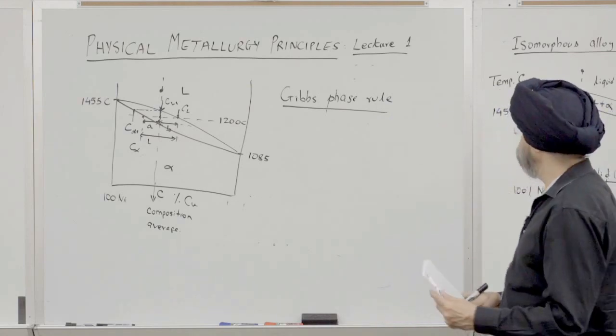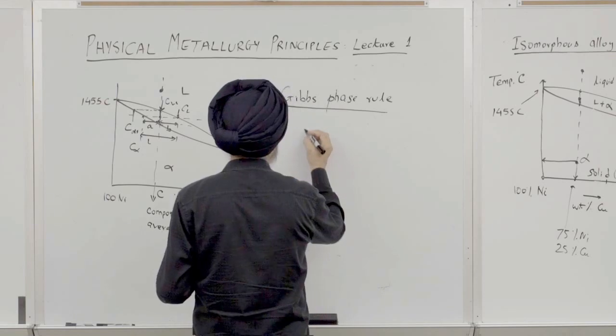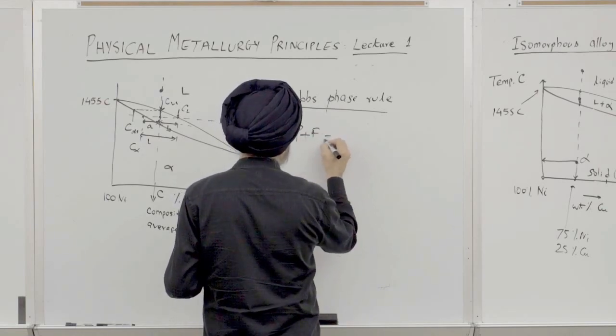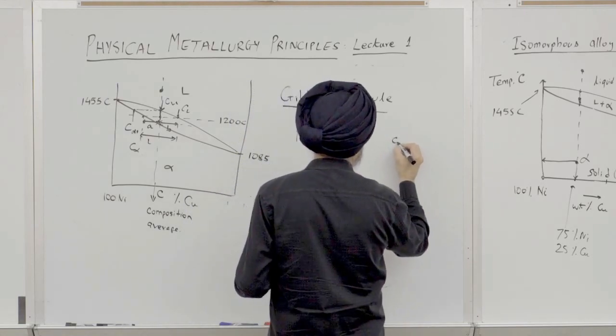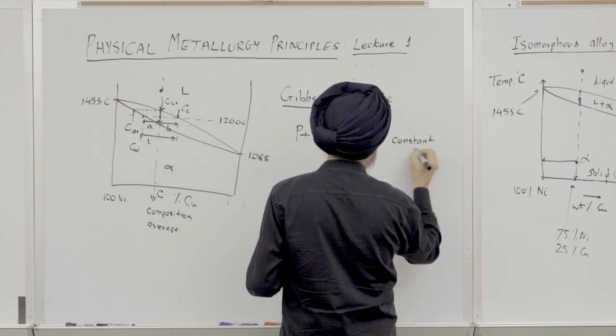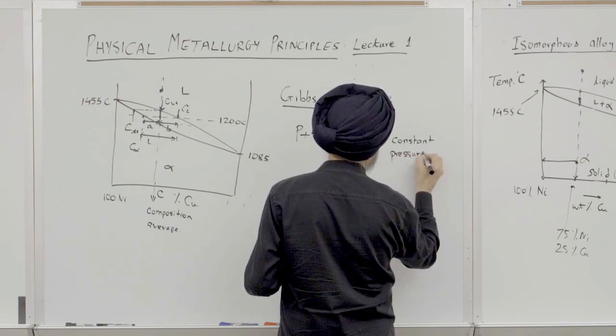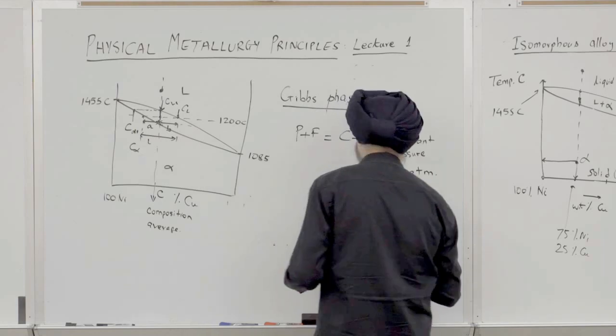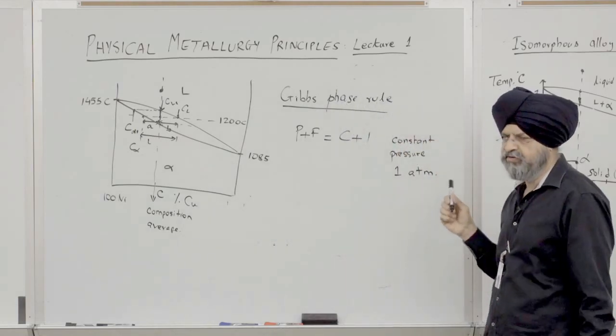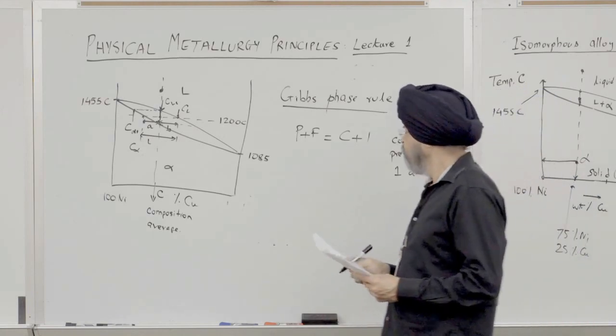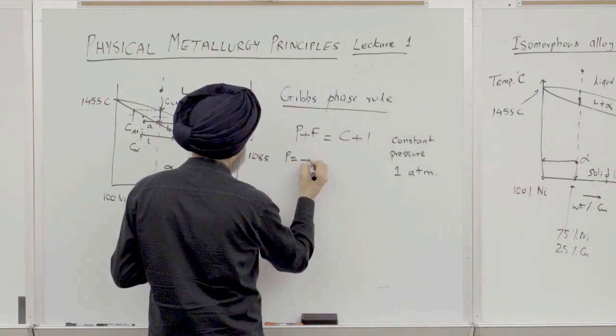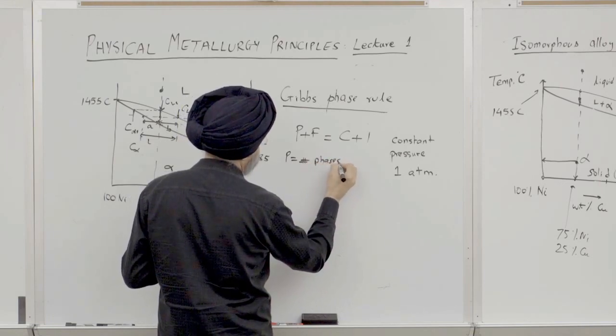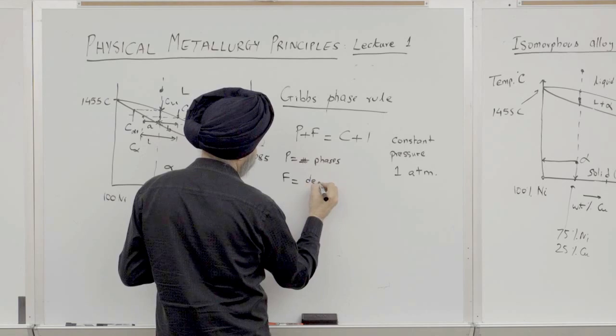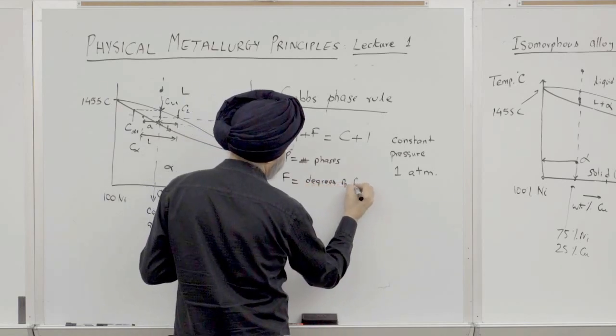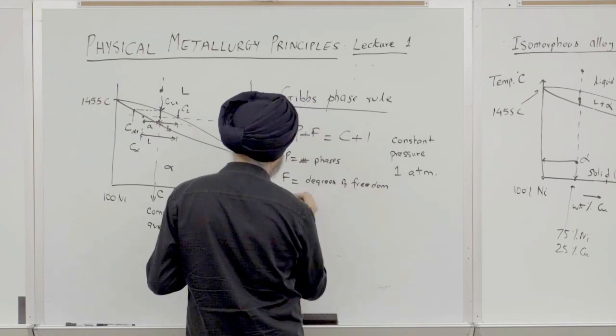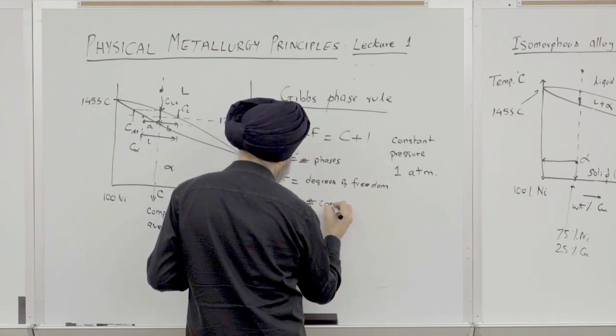But this is a little different. This is Gibbs' phase rule. What Gibbs' phase rule says is that P plus F is equal to C plus 1 under constant pressure, because metallurgy is done under constant pressure, mostly 1 atmosphere. All your blast furnaces, your heat treating, everything is done under a constant pressure of 1 atmosphere. P is the number of phases. F is degrees of freedom; we'll explain that. C is the number of components.